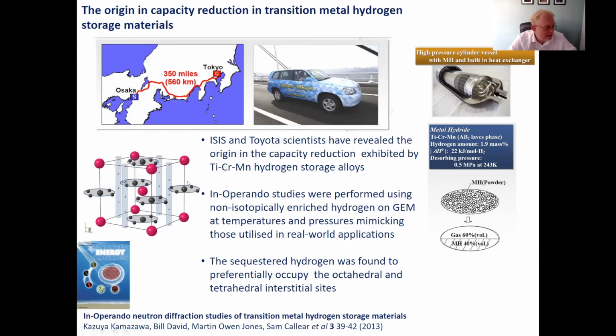And we worked out that you could get these channels, and if the hydrogen went in these channels, then it was free to move. But if it went in these square planar ellipsoid sites, then it was fixed and immobile. And we were able to solve that problem through a combination of neutron and X-ray diffraction.